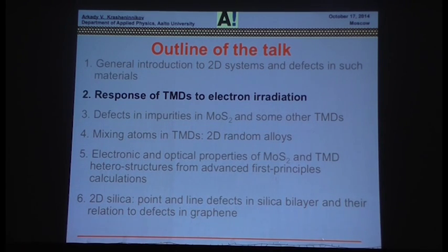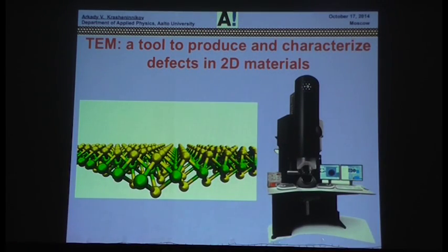As Dmitry mentioned already, these materials are routinely characterized using a transmission electron microscope. This is again a single sheet, and energetic electrons go through it. The first thing a student learns when starting quantum mechanics is the dualism of electrons, the particle-wave dualism. On the one hand, the electron is a wave, which is how you get the image. On the other hand, the electron is a particle. It has energy. It can knock out atoms from your target and create defects.